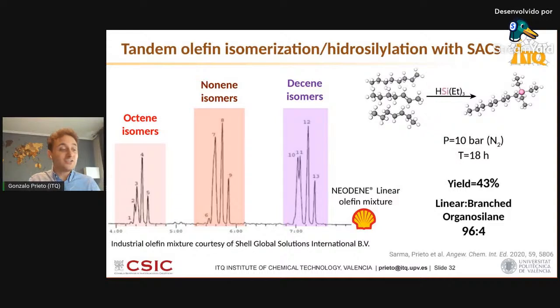So, and this is my last slide, this triggered us to try this tandem system in a relevant and tough, I would say, feedstock. That's an industrial mixture of internal and terminal olefins, in this case C8 to C10 olefins, which was very kindly provided by Shell. That's what they call the Neodene products. Those are olefin mixtures which come from metathesis upgrading of ethylene oligomerization processes through the so-called SHOP, Shell higher olefin process, patented and operated by Shell. These are relatively low value mixtures because of the coexistence of a number of internal and terminal olefins.